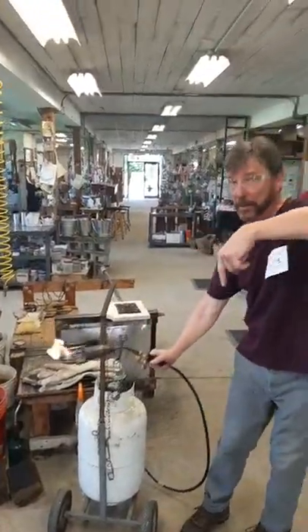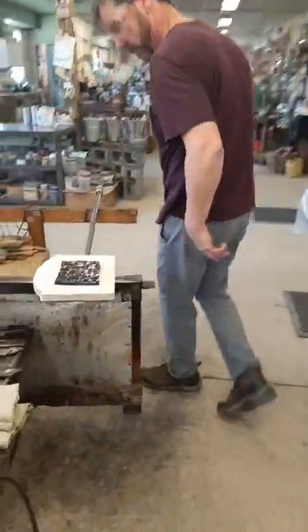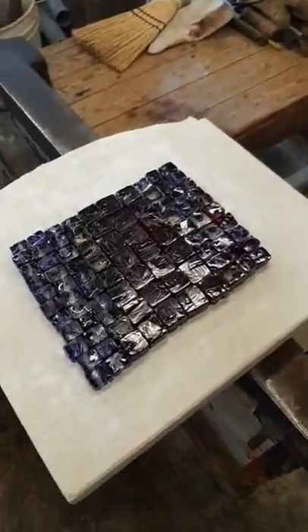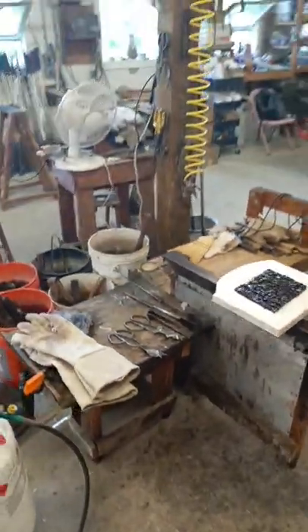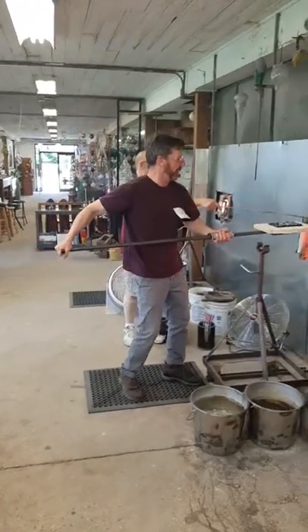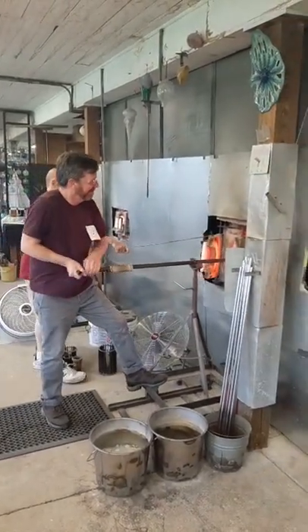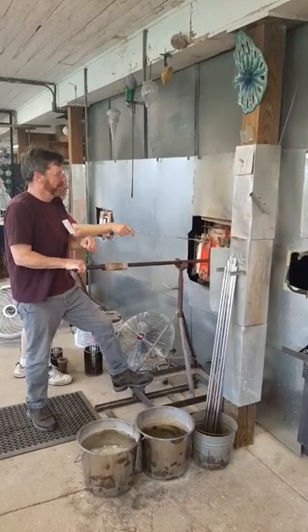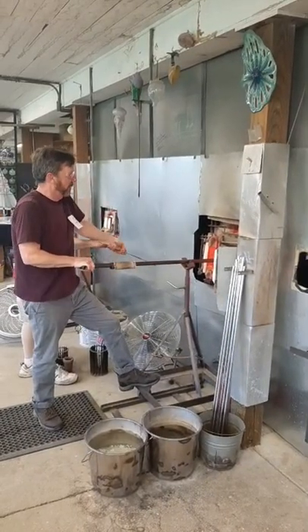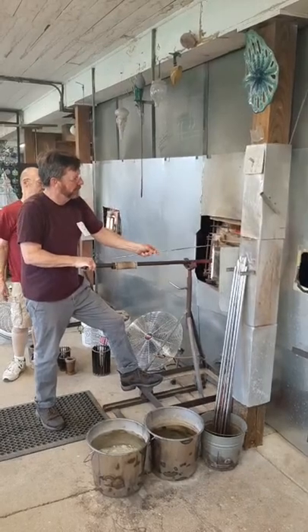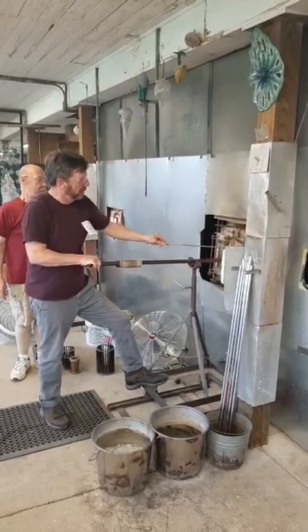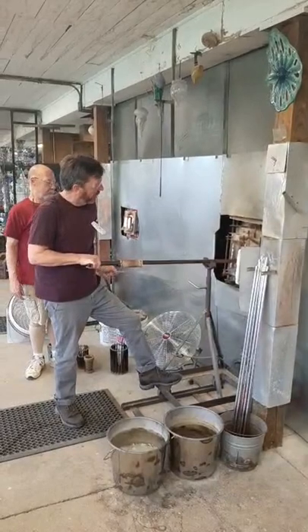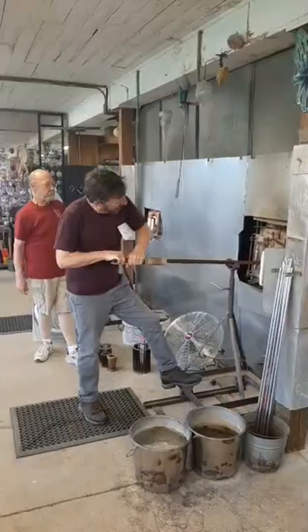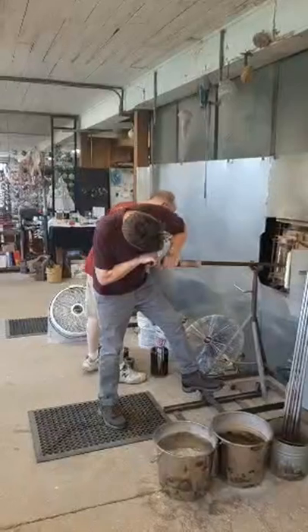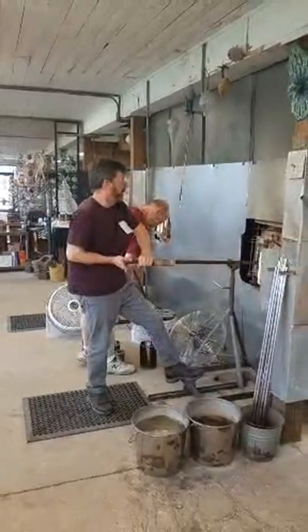Now that we torched the frost off of that, you can see the pattern a little clearly. Yep, that took some of the frost off. There you go. Okay. So as I mentioned, the burner is on one side of the glory hole. So it strikes one side of the plate first and is blocked from striking the other side. Also, the edges pick up the heat and not the middle so much. So that's why he turns the plate to expose the other side and then uses our propane torch to heat the center of this collection of glass so that it all gets to the same temperature.